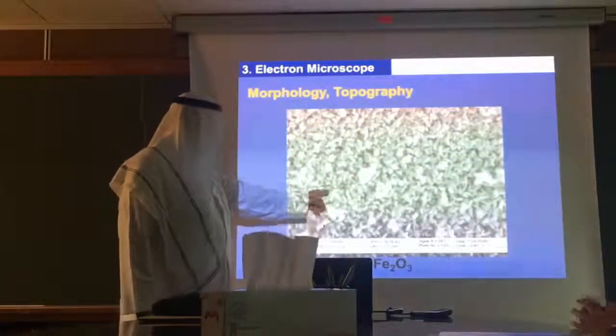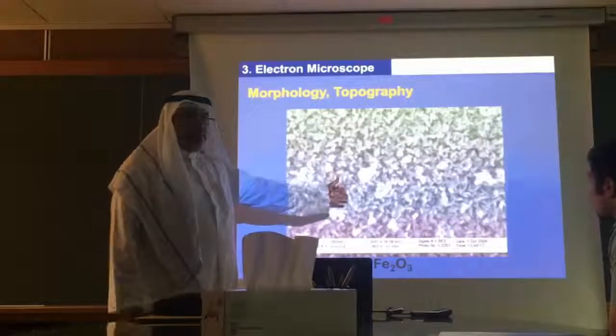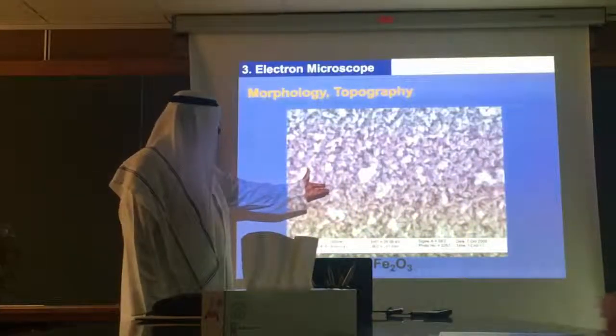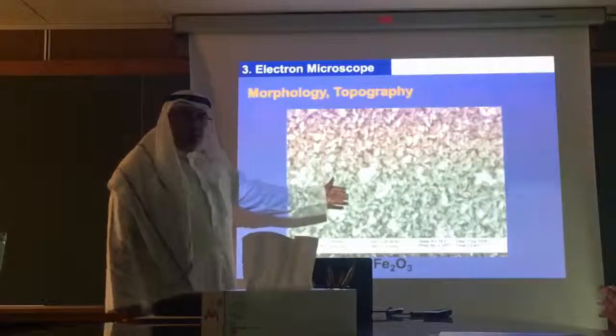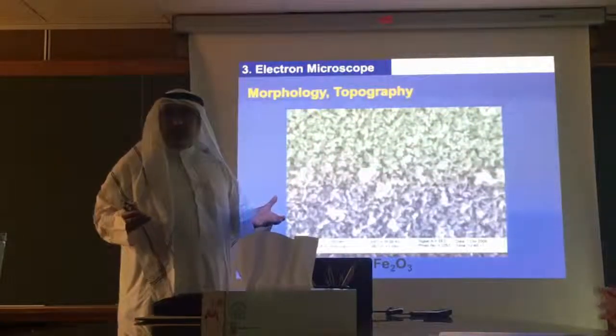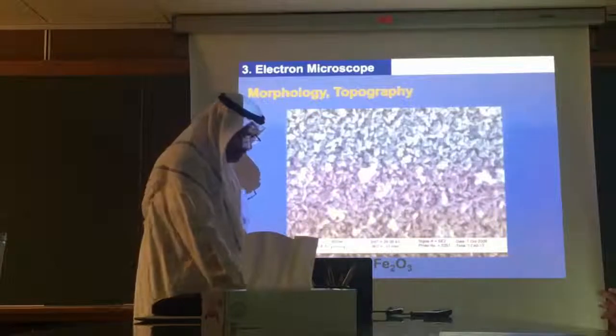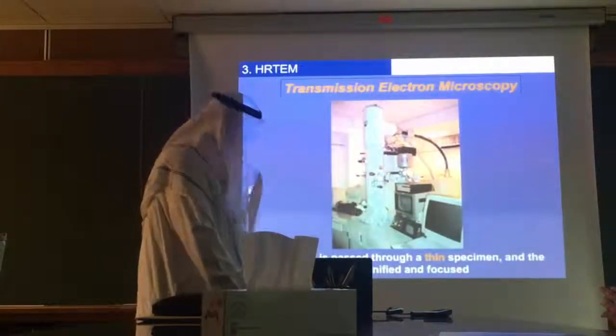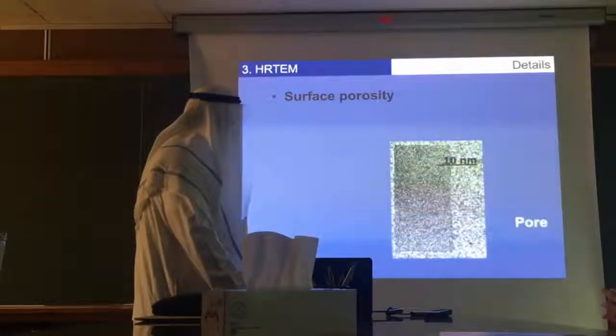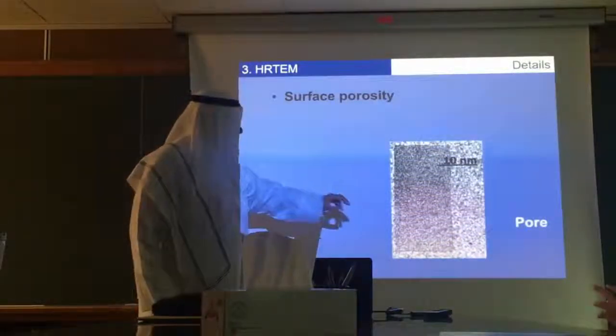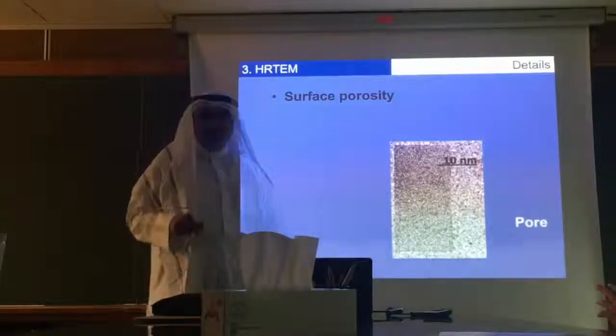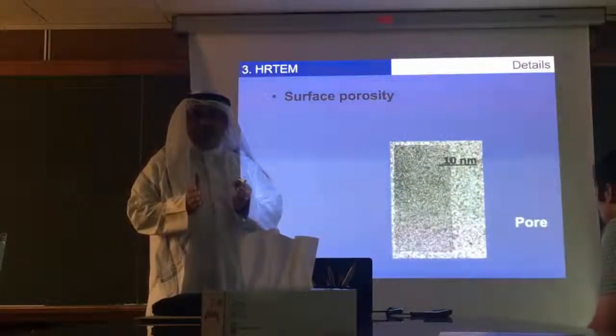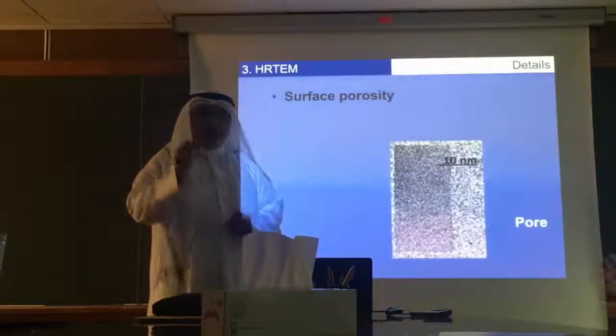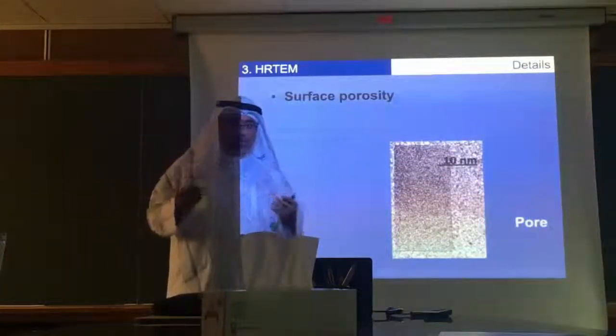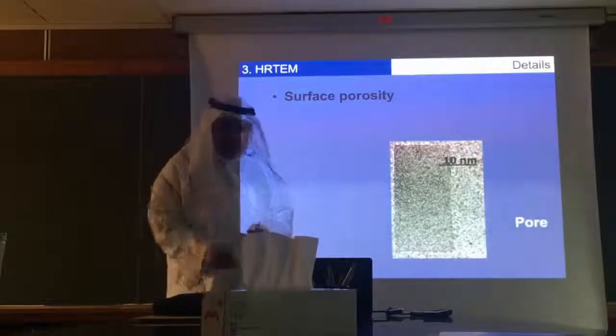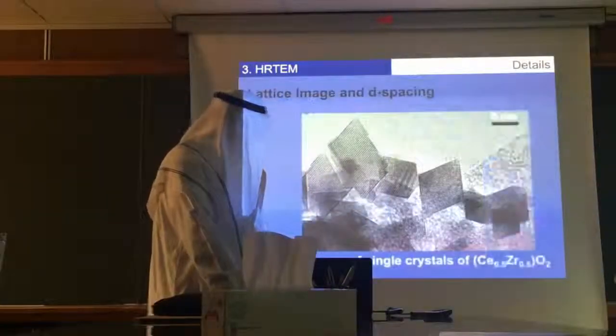This is a picture of iron oxide arranged in a shape very close to the rice shape, actually. You can see from scanning electron microscopy the morphology very clearly, the shape of the particles. This is the image of the device that you have, TEM. For the high resolution TEM, you can go to higher resolution so that you can even see the small pores, because the resolution can reach 0.1 nanometer or 0.2 nanometer. If you want to know whether your material is highly porous or not, and what is the size of the porosity, you can do it with this device.